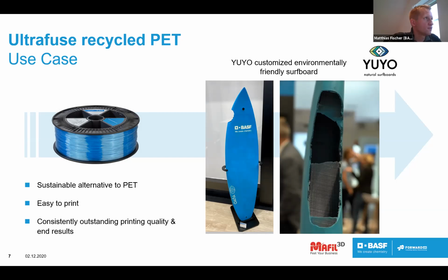It's about a surfboard from the company YUYO. And here they use this PET filament for the core of the surfboard. Of course, to get the right mechanical performance, the right stiffness, a coating was done afterwards as a strong structure. But it's a very nice example of how such a sustainable product can be part of such a customized, environmentally friendly surfboard.